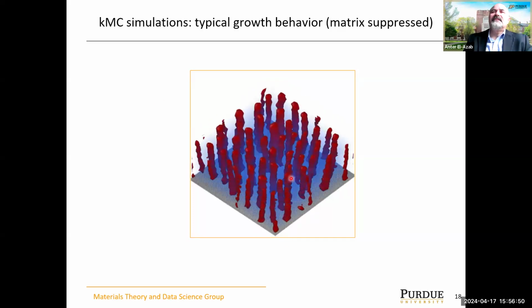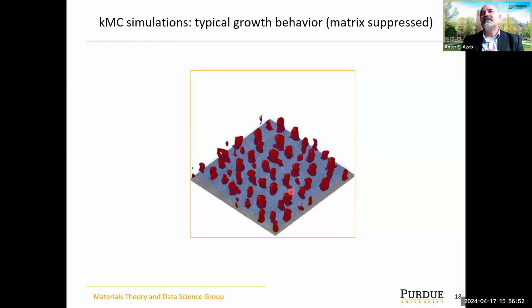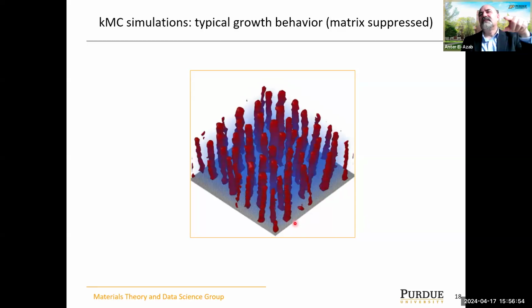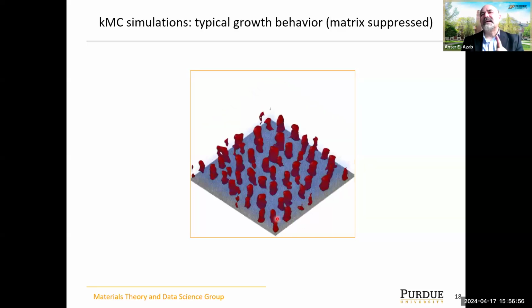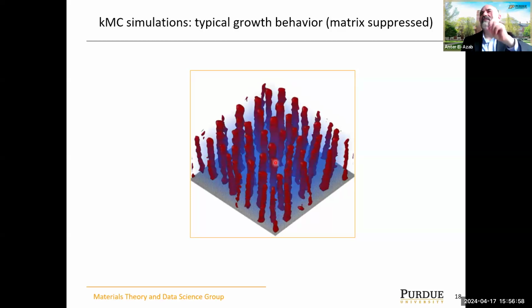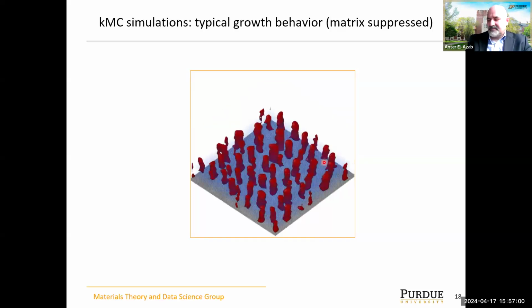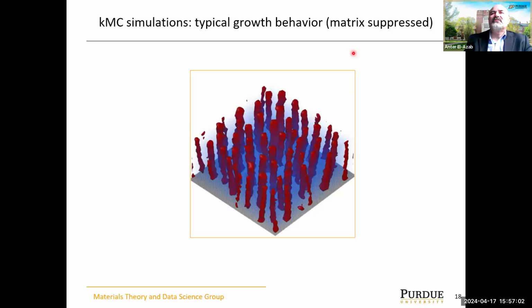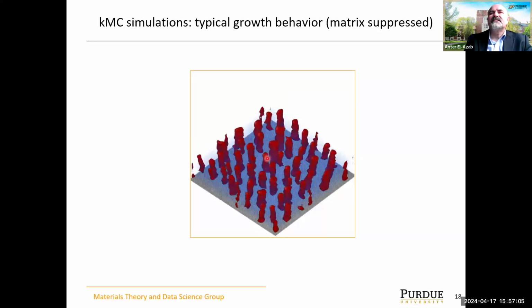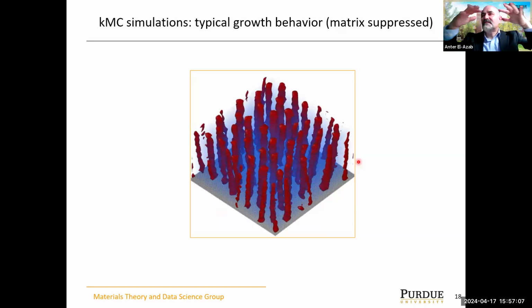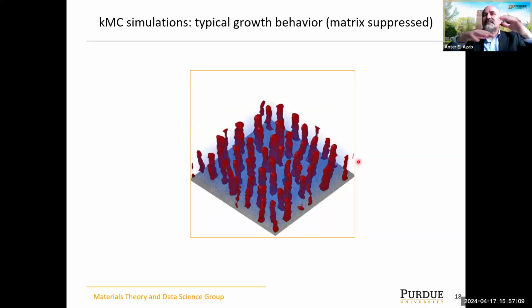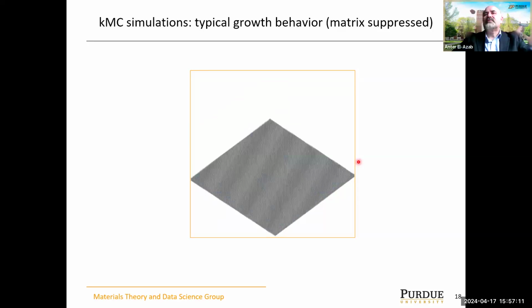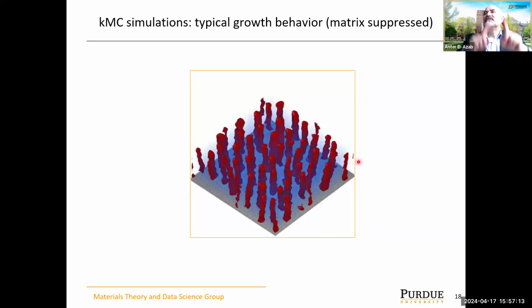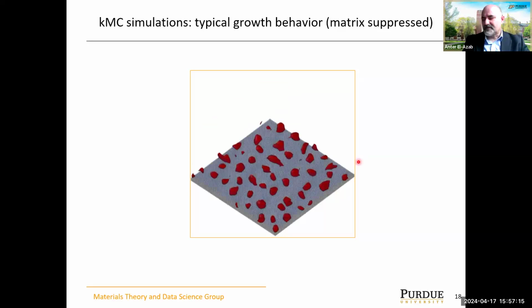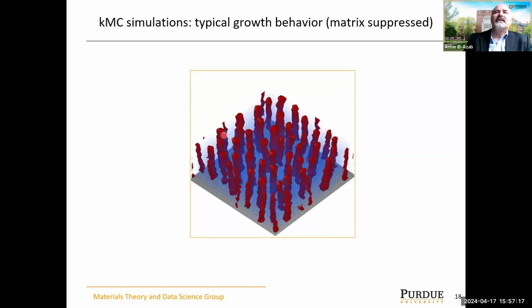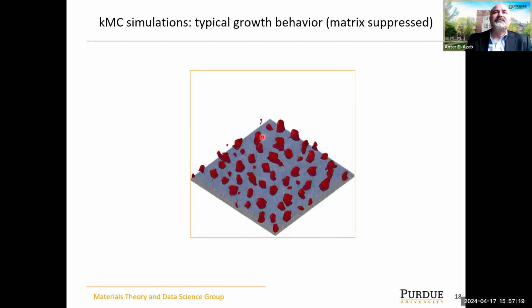Actually, anybody who knows phase thermodynamics and kinetics of island formation would predict that these things are going to grow vertically like this from the beginning. So that's the growth of the pillars, the red phase here. The matrix is also growing concurrently or simultaneously, but it is suppressed in order to view the pillars and their self-organization in the matrix, as you see in this movie.